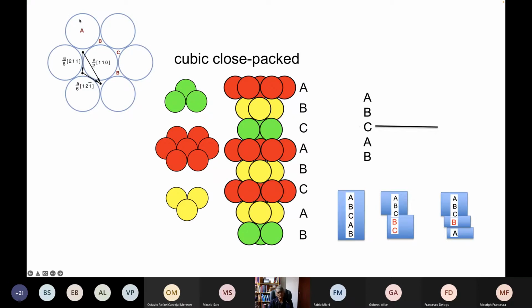So this plane here is our close-packed plane, and I'm stacking them in a sequence A, B, C, A, B, C, illustrated over here. So this represents our face-centered cubic crystal structure of austenite. And this is a repetition of that stacking sequence, A, B, C, A, B. And now I'm going to displace one half of that crystal relative to the other by a/6 [112], and that results in this. So we have A, B, C, B, C, and then conduct another displacement on an adjacent close-packed plane, and that results in A, B, C, B, A. So notice that about this twin plane C, I have reflected the crystal structure. So B reflects to B, A reflects to A. So this is our mechanical twin, and its lattice is a reflection about the twin plane of the parent structure.